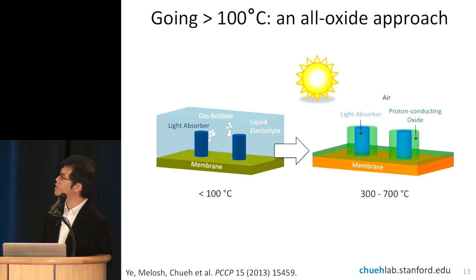And for the last part of my talk, I want to discuss how to go above 100 degrees Celsius. So if you don't pressurize the water, basically it will boil at about 100 degrees Celsius. And we see that there is a benefit to temperature enhancement. And the next question we ask is, can we get more out of it by going above 100 C? So we needed to replace the water with a solid state electrolyte. And what we've developed here is an all oxide approach, replacing water with an oxide-based solid electrolyte.